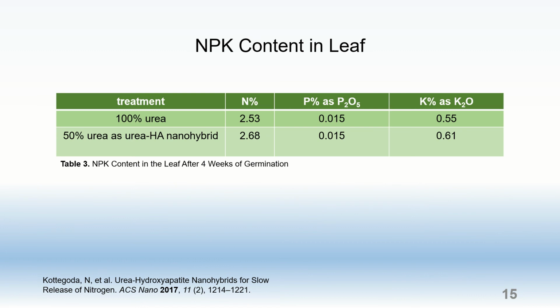Additionally, the nitrogen, phosphorus, and potassium contents of the leaves obtained from the rice paddy plants 4 weeks after germination were compared for the plants with the recommended amount of urea and the plants with 50% of the recommended amount of urea, and this was added by the urea-coated nanohybrids right here. The results obtained are shown in Table 3. The table shows that the amount of nitrogen uptaken by the plant is maintained in the urea-coated hydroxyapatite nanoparticles, even at half the recommended amount of nitrogen.